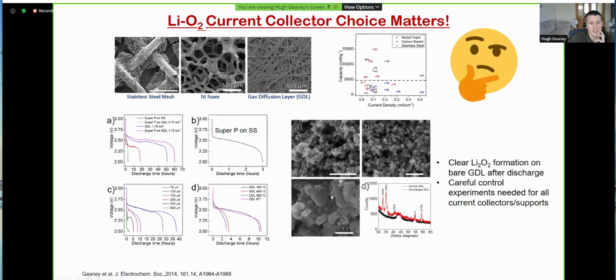So these are characteristic shapes. They're called toroids. Very often they're donut shaped, and that tends to be the way that the lithium peroxide forms on current collectors. So I won't dwell on this too much. If people are interested in the results, they can ask during the question section. But what we found clearly was that lithium peroxide was forming just on the bare GDL, as it's called, and inflating the capacity numbers.